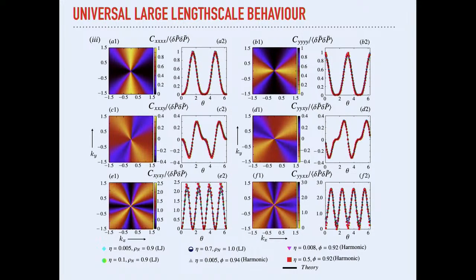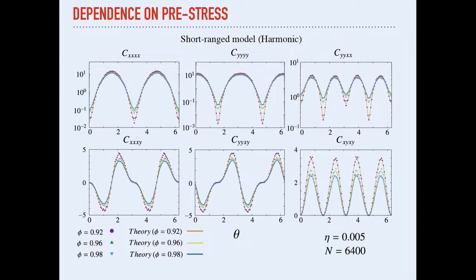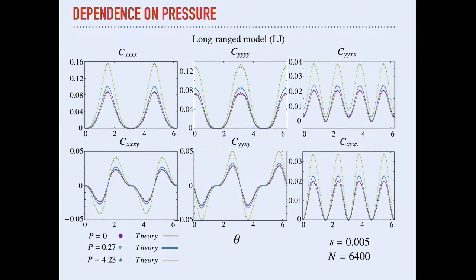There is a small difference in the angles depending on whether you are in the crystal or not, which we are still investigating. But at very large length scales, integrating around small q, you get universal correlations. You can divide by the pressure correlations, and all data collapses onto one master curve regardless of what packing fraction or disorder you started with — because the magnitude of stress fluctuations can be exactly normalized by pressure fluctuations. This is the main result: all components of the stress tensor can be predicted exactly, and for both the Lennard-Jones and harmonic models, scaling by pressure squared gives universal correlations.